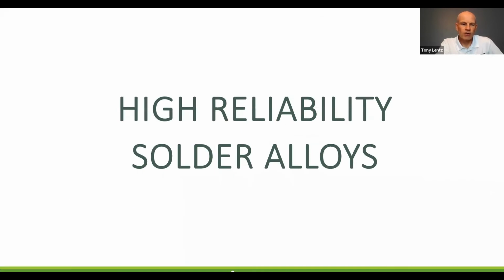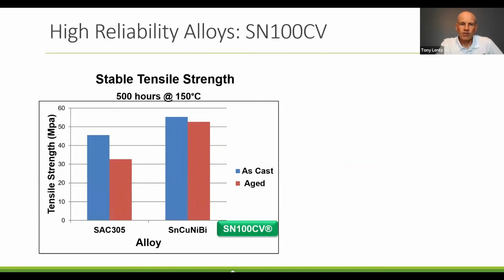So now I'm going to switch gears and talk about high reliability solder alloys that are available with this solder paste. So here's some data on SN100CV, which is tin, copper, nickel, and bismuth, shown on the right. And then SAC305 is shown on the left on this chart. And this is a tensile strength chart. The blue bar is as cast or freshly prepared ingots. And then the red bars are aged 500 hours at 150 C. You can see SAC305 loses tensile strength as you age it, whereas SN100CV does not.